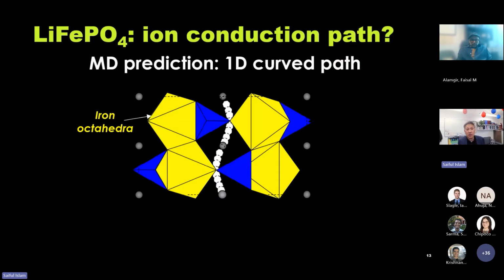Another example is the lithium iron phosphate that I mentioned. This is a slice through the structure. The yellow polyhedra are the iron octahedra. The blues are the phosphate groups, and the greys are the lithium ions. And using computational techniques, we predicted that it was a 1D lithium ion conductor, but it was actually following a curved pathway. So that was a nice, clear prediction. That was a clear prediction that we published before experiment.